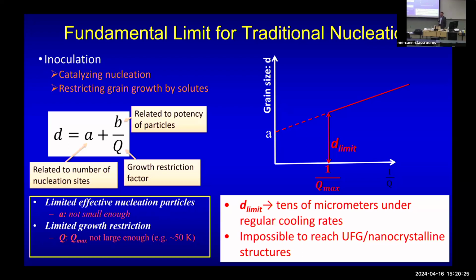That's why in traditional casting, you normally get hundreds of micrometers or tens of micrometers at minimum, really, right? You cannot get better than that a lot of times, unless you go really fast cooling. But when you go very fast cooling, you do not go to mass production, right? So this is the dilemma there.